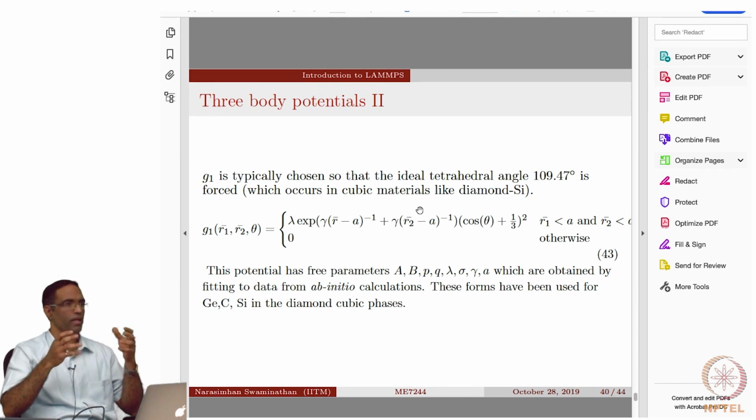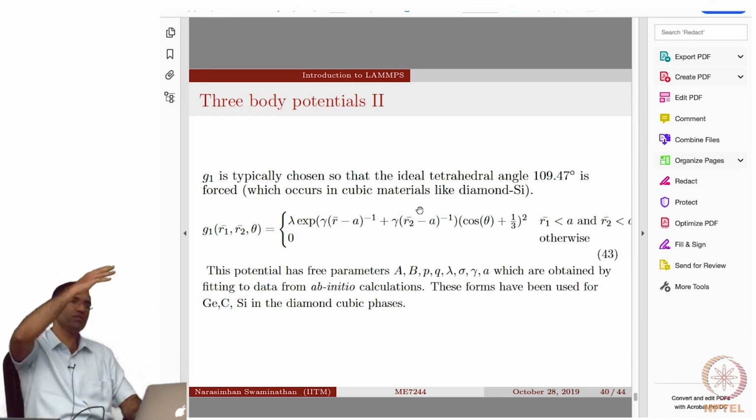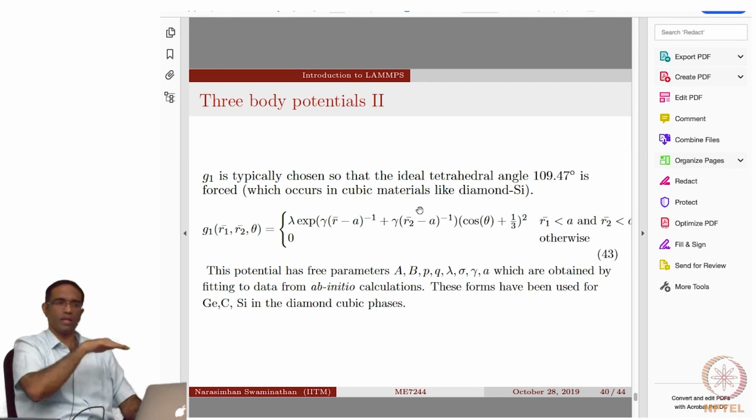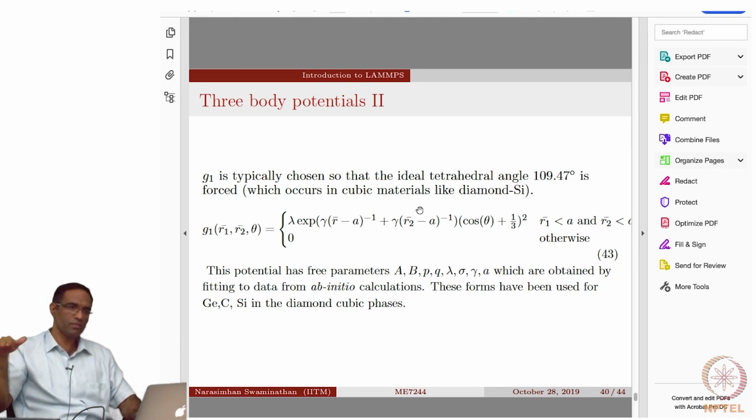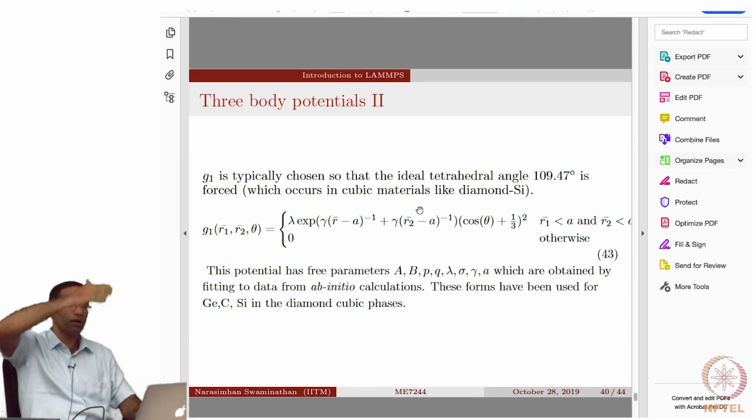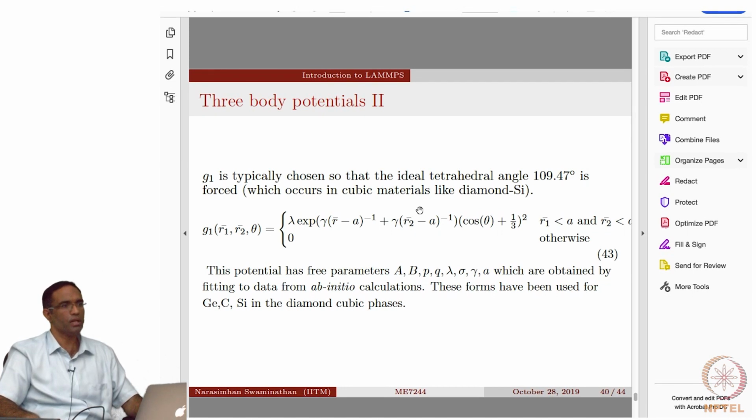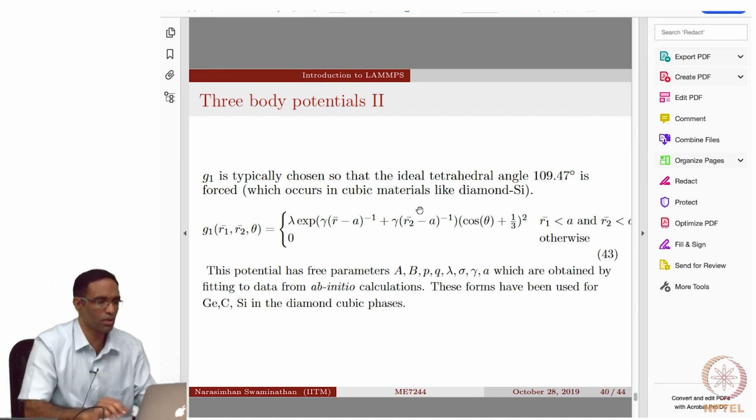silicon, not to do anything spectacular, but simply to print the variation of the energy for various lattice parameters. When you plot that, you should get a U-shaped curve, and the value of the lattice constant at which the energy is a minimum is the lattice constant you get for that particular material for that potential. Okay, that's the goal.